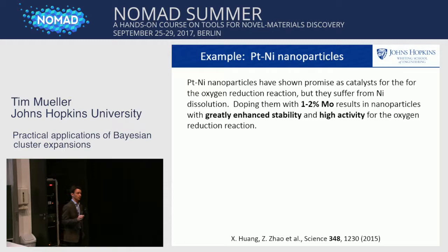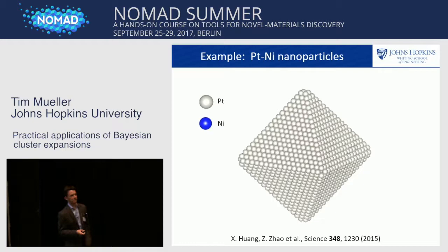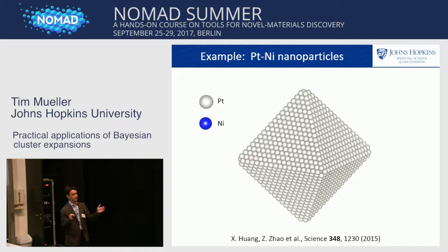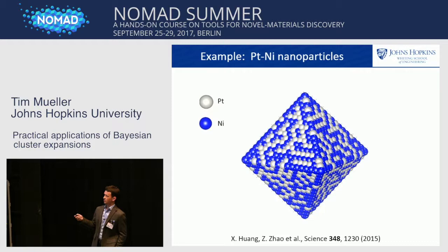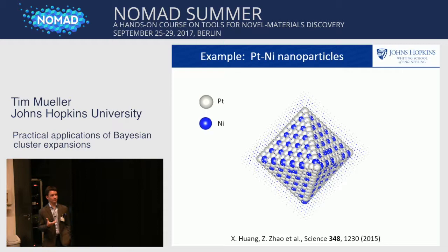And so what we get, so this is now just using the platinum and nickel in the nanoparticle. We built the nanoparticles to be the experimental shape and size. So this is about 4.2 nanometers edge length. They're octahedral nanoparticles. And if you drill down here in equilibrium, you find that it's similar to what you see in the bulk or the extended surface. You have this disordered second layer, and then as you go down further, you gradually get more and more ordered until you get to what you would expect to see in the Pt3Ni phase diagram, which is this well-ordered structure.